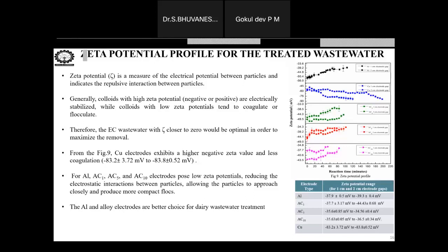What may be the reason? Why can't we go for 20? I made 15% also, but the electrode I got was brittle. It will break very fast. So the optimum concentration is why I saw 8 to 10. If I go beyond 10, the value will not be stable, and it will provide a small voltage. Because of that.